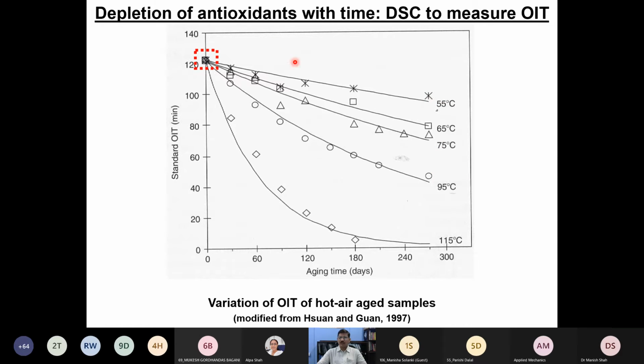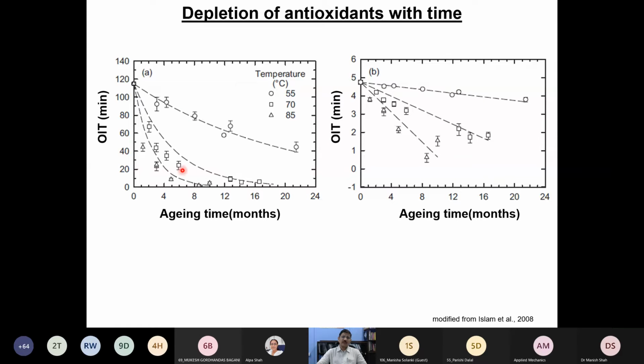in air how the oxidative induction time is going to deplete over a range of temperatures. And this is, in case of a leachate, 55 degrees and 70, and then this one 85 degrees. And the moment I plot the OIT on a logarithmic scale, then I can see this particular variation. So if the OIT is initially this much, I know the rate of depletion of the OIT and how much time is needed in order to touch OIT equal to 0. That means that is the onset point where your membrane is subjected to severe degradation.